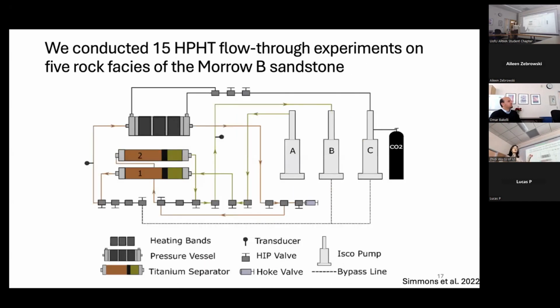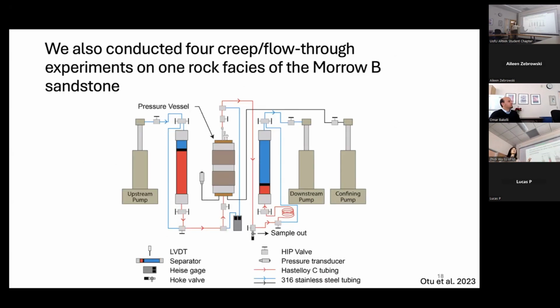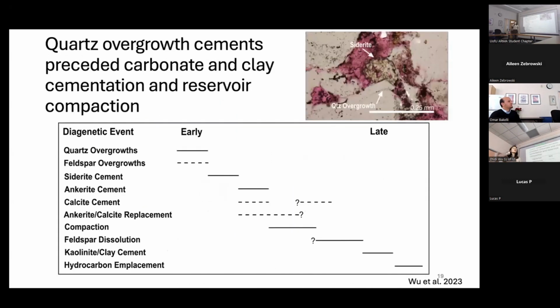For this type of flow-through, we've done 15 experiments. For this one, we did 4 experiments, four samples. So that's 19 samples in total. And those 19 samples are all Morrow B samples collected from the Farnsworth unit, and we categorize them into 5 rock phases. The different rock phases are featured by the porosity-permeability relationship and the lithology, which means how big the pore size is, or where those pores are located, and the chemical composition of the rock. So there are five categories.